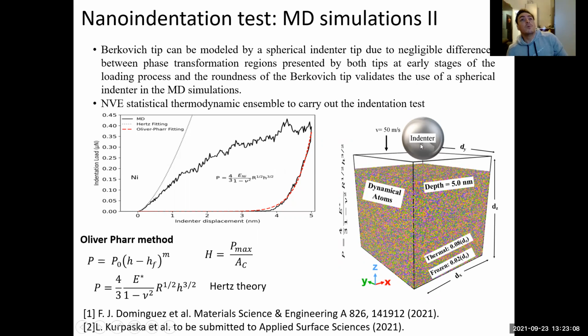So now, when performing MD simulations and doing the loading process and the unloading process, we also obtain the typical load-displacement curve that experimentalists can also obtain. From the MD simulations, we can obtain many quantities, and we can study all of them. Here in this part, you can even track the simulation. Here you have no interaction. This is only the vacuum. And then here, this is the surface.